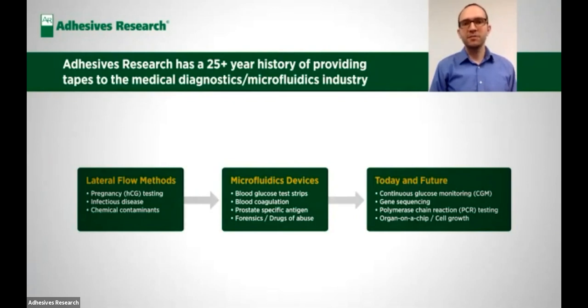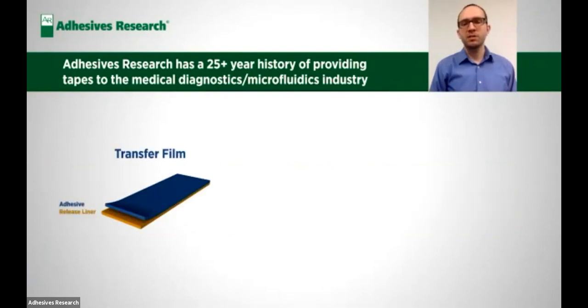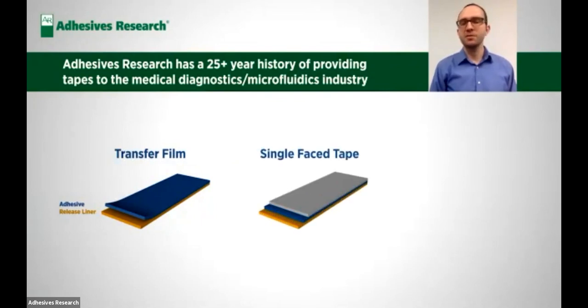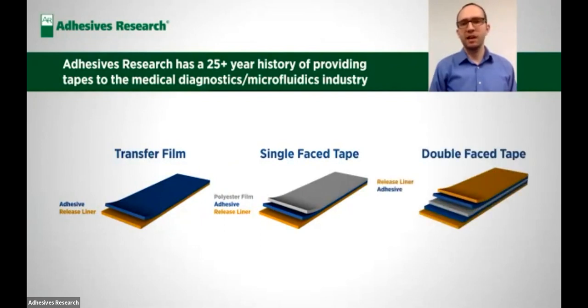Before I get into the rest of the presentation, I'd like to briefly review the types of pressure-sensitive adhesive tapes that are available in the marketplace. One would be transfer films, in which a single layer of adhesive is placed on a release liner. This can be used to bond two materials together, and this is your best option for forming a very thin channel height with a pressure-sensitive adhesive tape. There are also single-faced tapes in which a polyester film or another type of backing can be used to support the tape. These would be bonded on only one side, and they would have a release liner protecting the adhesive. And then there are double-faced tapes in which the carrier has adhesive on either side, which is protected with a release liner.